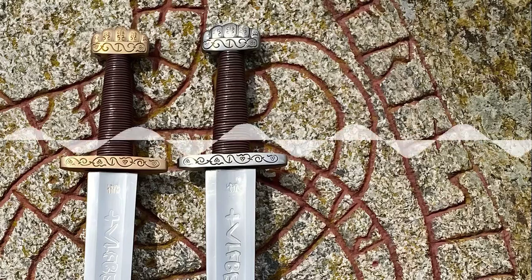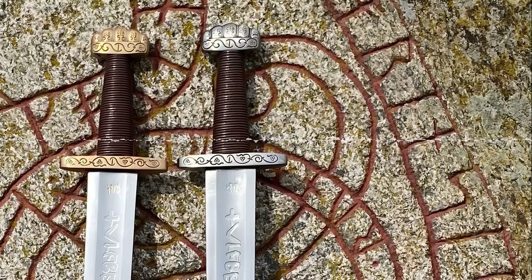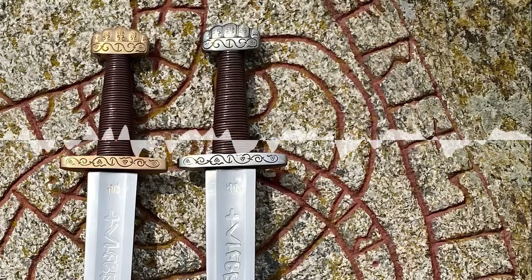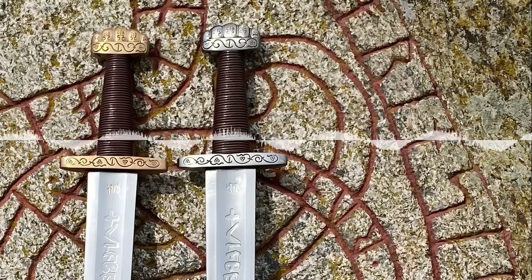Other blades shattered in close combat, but the Ulfberht was far more resilient. The slag-free steel broke much less often than other swords of its time. That's how it was described, at least. And when you consider how many of these swords have survived over 1,000 years, there must have been something to it. It's the combination that matters. Better steel, better shape, better balance. Altogether, it produced a weapon that offered real advantages on the battlefield.